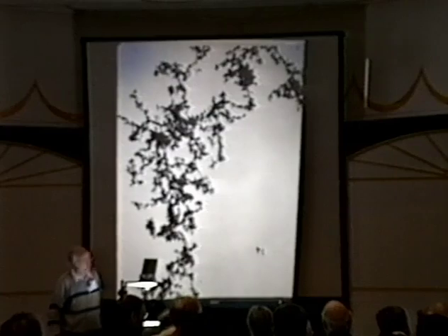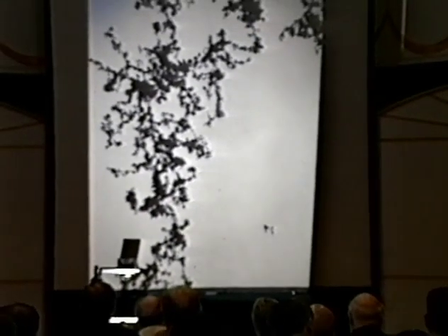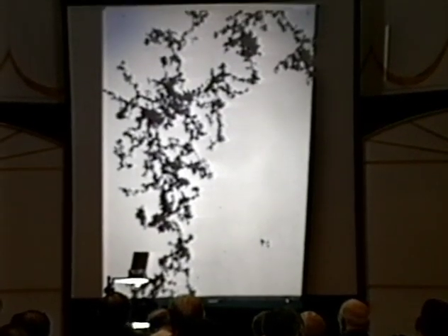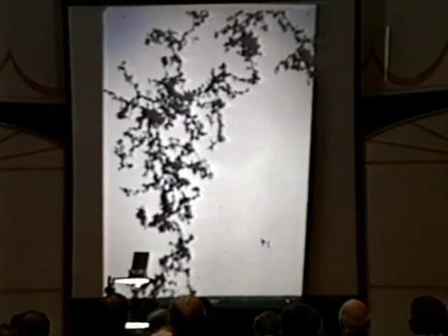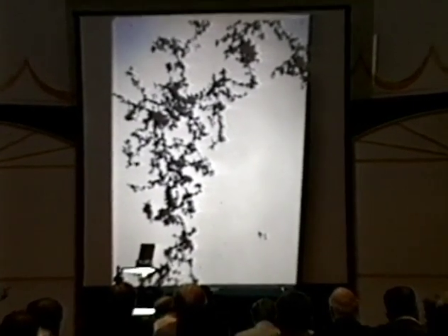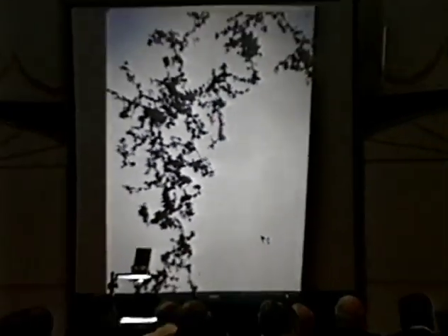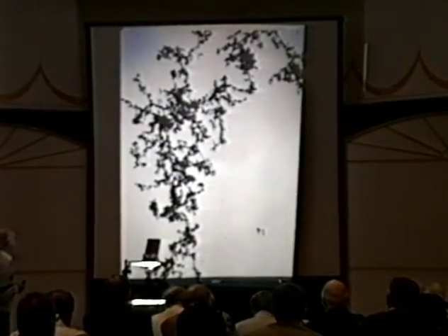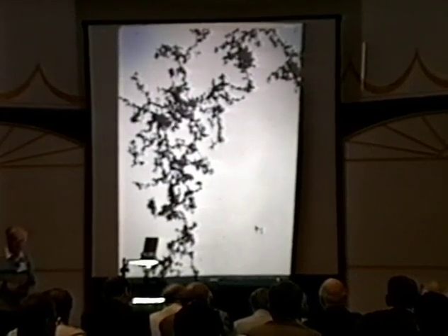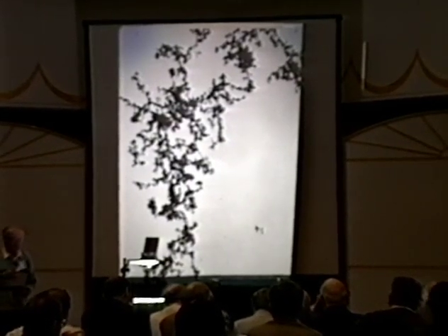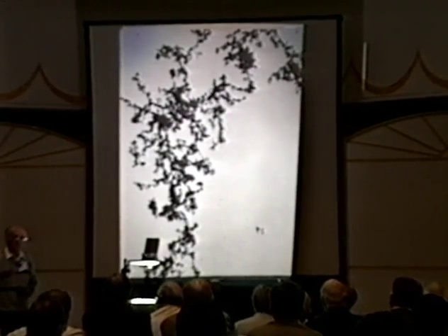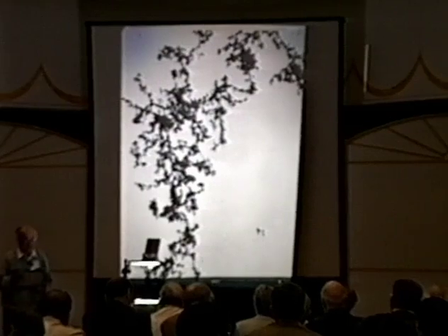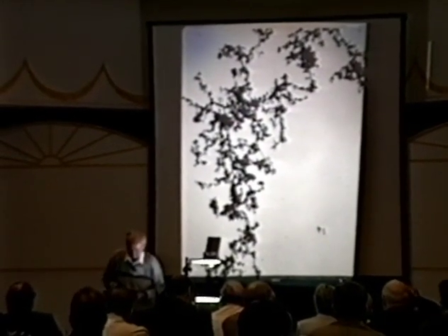Here you see an electron micrograph of a preparation which I have made by vaporization of titanium in argon of 1 centimeter of mercury pressure. You see small titanium particles about 10 nanometers or 50 nanometers in diameter. These are monocrystalline particles. They are arranged in chains with many ramifications. In this manner, one gets a very loose, sooty deposit, which is very absorptive for the uptake of hydrogen isotopes.